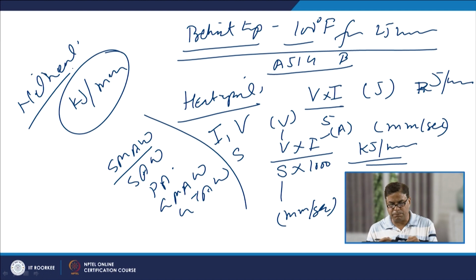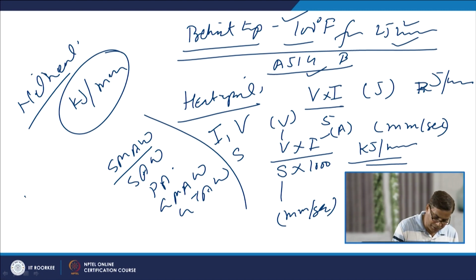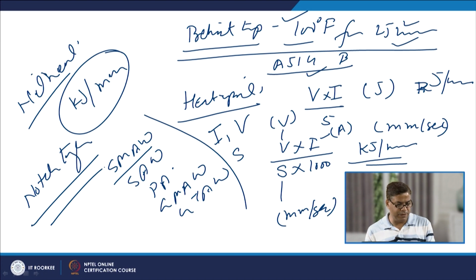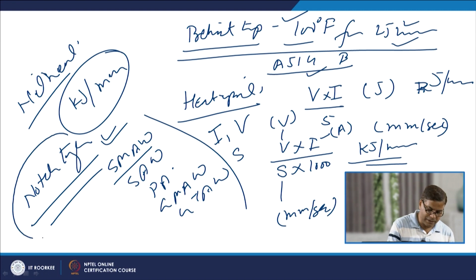So, through the welding procedure specification for a given preheat, during the welding of plate of given thickness of the given composition, we try to identify the heat input so that we are able to have the required notch toughness. Most of the heat inputs are given with reference to the notch toughness value, that the combination of the welding parameters, preheat temperature for a given thickness of plate of a given composition will be offering us this much minimum notch toughness, because most of these steels during the welding experiencing drop in toughness, that is why notch toughness is considered as an important criteria.